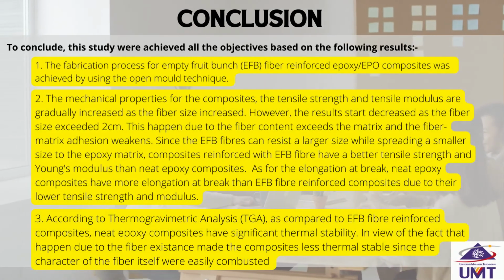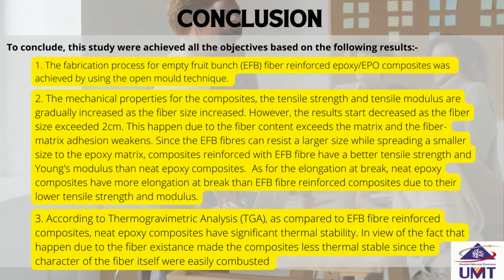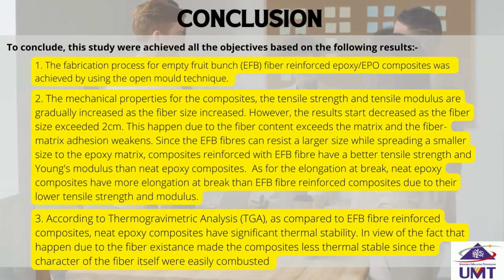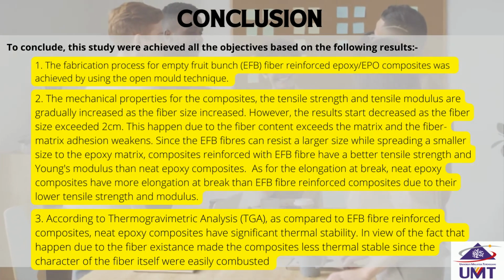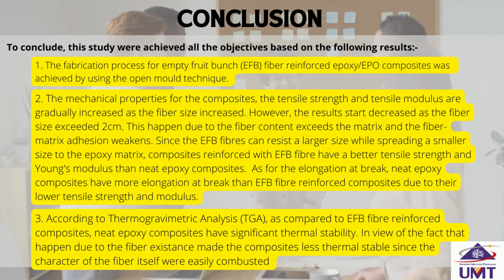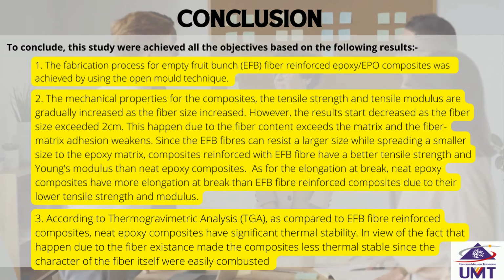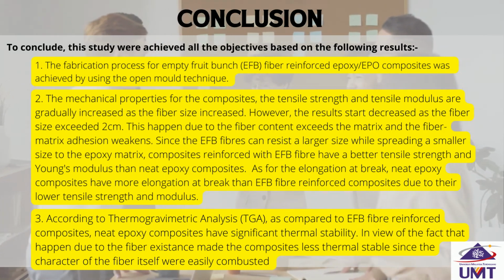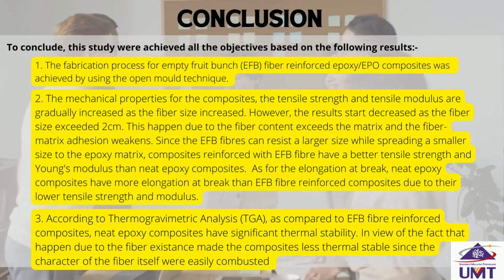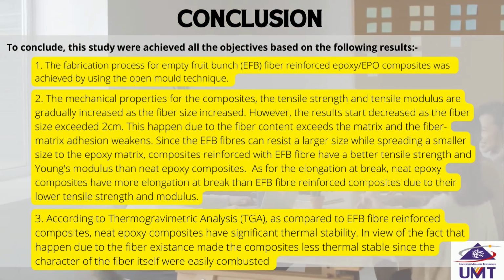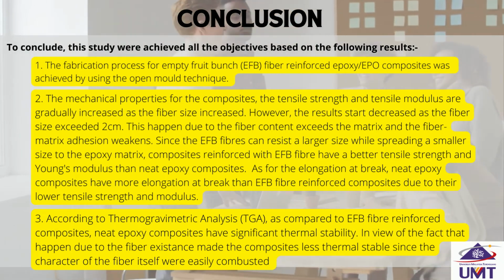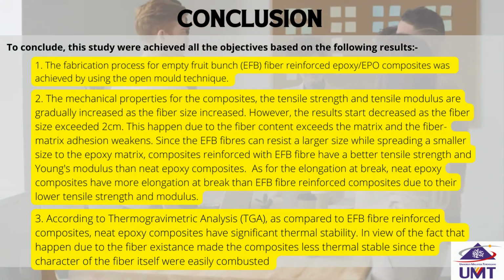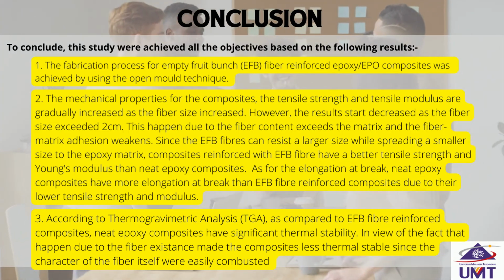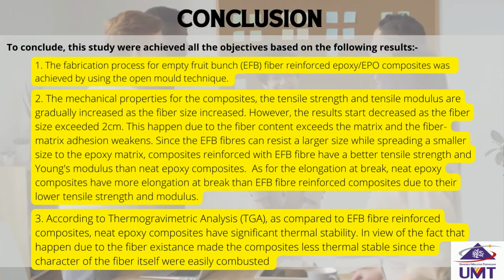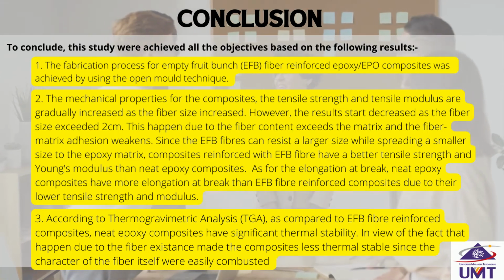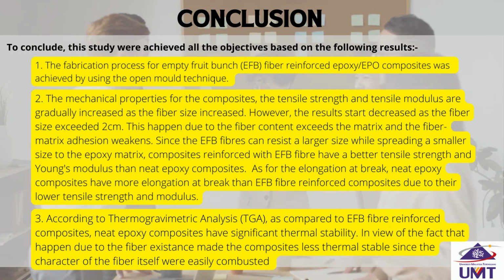As a conclusion, this study achieved all the objectives based on the following results. First, the fabrication process for empty fruit bunch EFB fiber reinforced epoxy EPO composites was achieved by using the open mold technique. Second, for the mechanical properties of the composites, the tensile strength and the tensile modulus gradually increased as the fiber size increased. However, the results start to decrease as the fiber size exceeded 2 cm. This happened because the fiber content exceeds the matrix and the fiber matrix adhesion weakens.